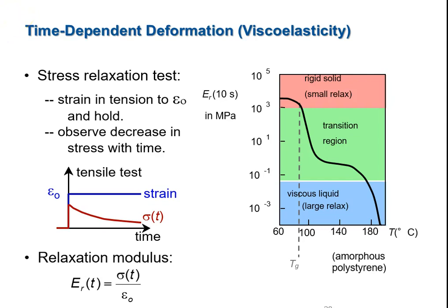Polymers all have enough amorphous material to have a glass transition temperature, even if they have a high fraction of crystalline material. The crystalline portion of the polymer can still melt. So you can have a melt temperature and a glass transition temperature, both. But the glass transition temperature will be lower in almost every case, and because it's lower, it's going to define the useful material properties. So glass transition is definitely the big temperature-dependent mechanical property that we're concerned with in polymers.